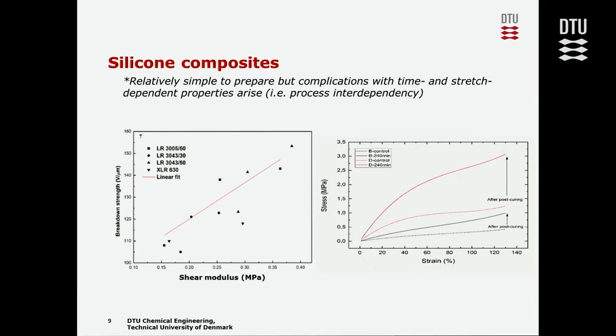Then for an actuator, it doesn't make any sense to add in the particles. On the other hand, if we look at the generator mode, then a high electrical breakdown field strength is very good to have. And the harder we make our elastomers, actually the better breakdown strength we get. So there is a possibility to use these silicone composites for generator materials, but not really for actuators.